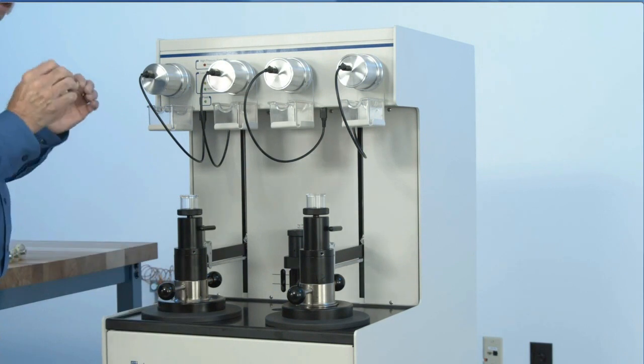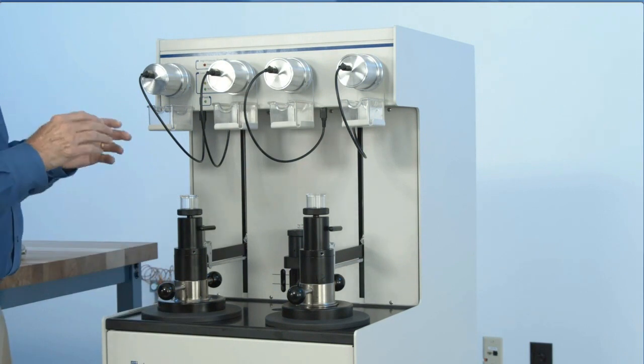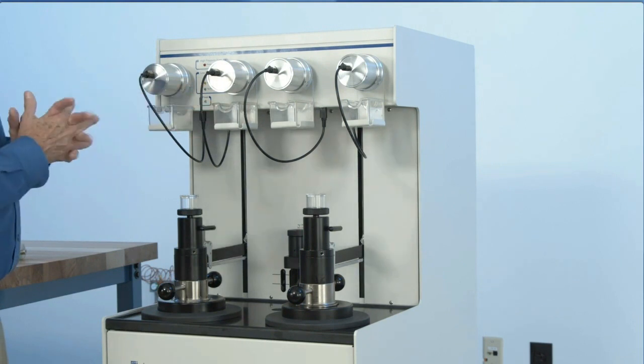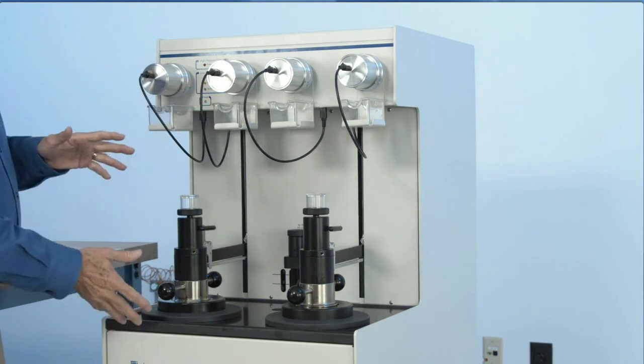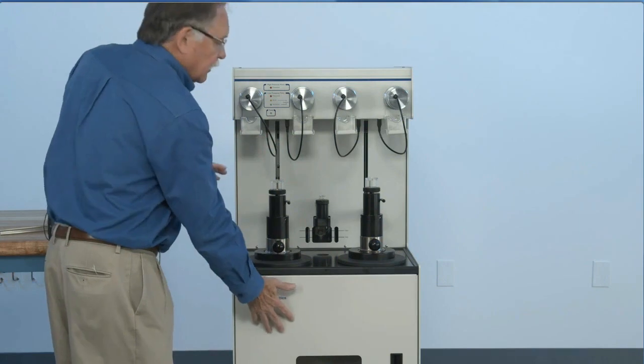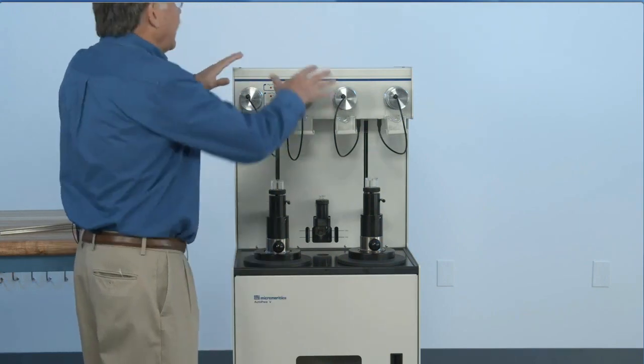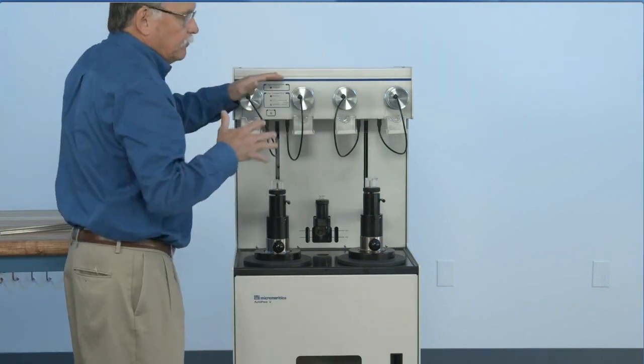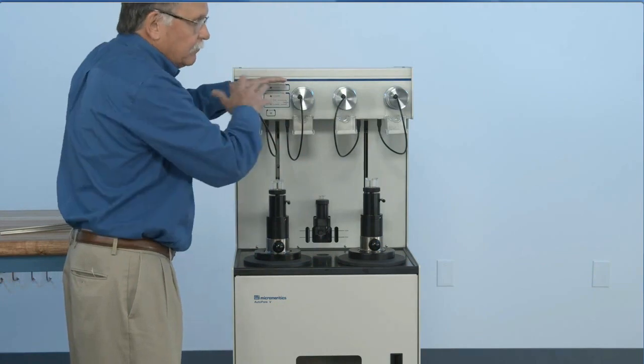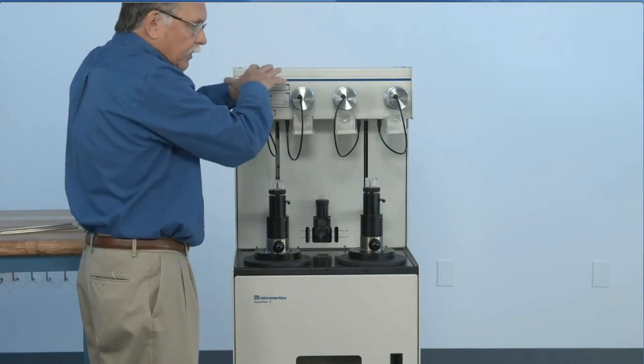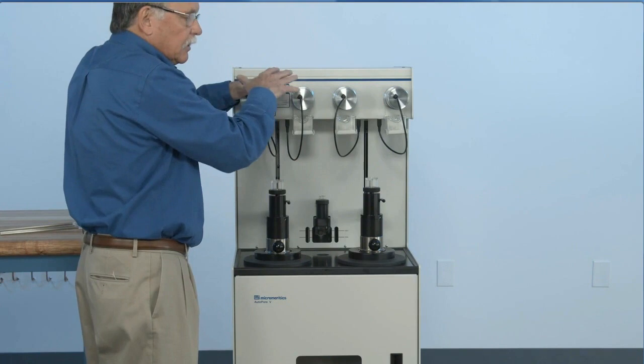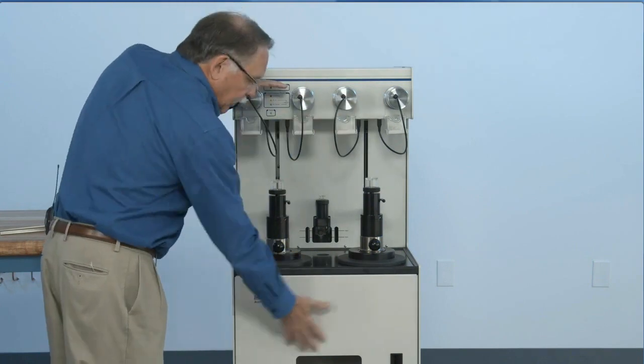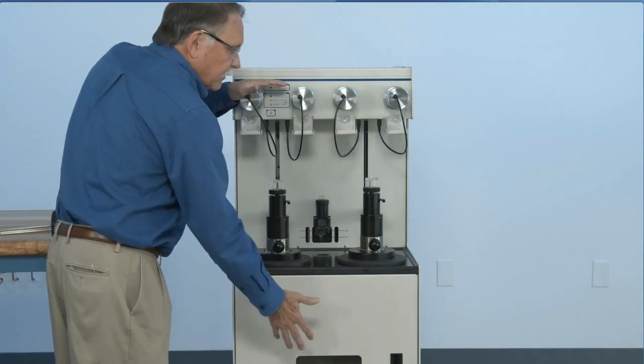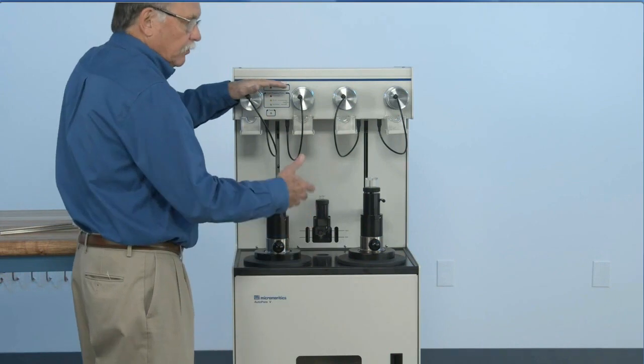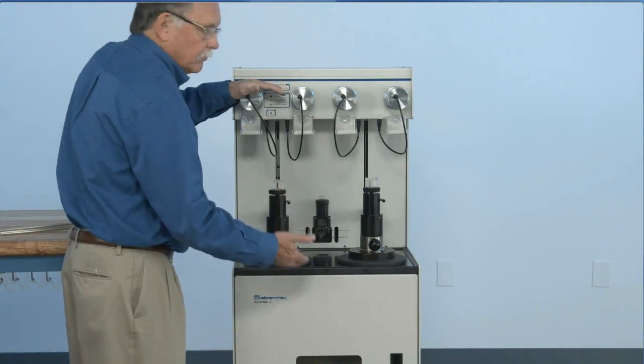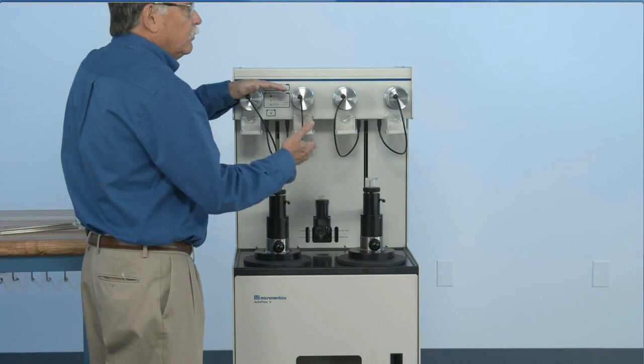But there's a number of new safety enhancements that have been added to the new AutoPore 5. One of those, I mentioned that we evacuate the sample. Since we're evacuating a system that previously had mercury in it, there's no significant amount of mercury in it, just a little residue, when we're evacuating the sample. On the vacuum pump housed in the bottom part of the instrument, there is a sorption filter that will trap any mercury vapors that might happen to make their way through the vacuum pump.